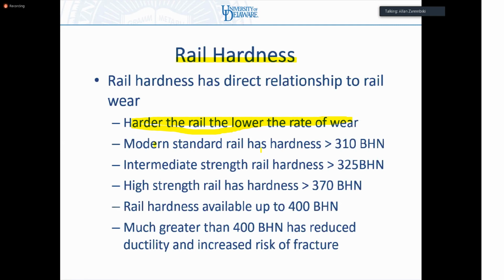Modern standard rail hardness is greater than 310 BHN, except for some of the lower section UIC sections, which may go down to 260 to 280. The AREMA rail does not allow any rail to be below 310. The UIC or the EN sections are moving in that direction, but they still allow some rails in the 280 to 300 BHN range. Intermediate hardness rail tends to be greater than 325. High strength rail, premium rail, is greater than 370, up to about 400.